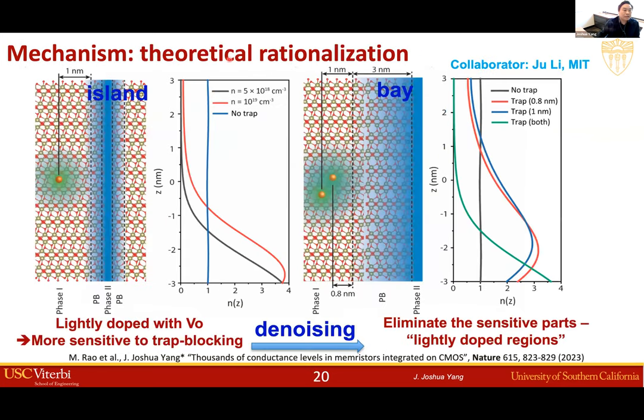So we further use a theoretical simulation to understand why such incomplete channel can give us the RTN noise in the island case and the bay case. Let's just look at the island case. This is an incomplete channel. And it turned out that this incomplete channel can be sensitive to a charge trapped nearby. So without a charge trapped nearby, the conduction of this channel is the blue curve. It shows a reasonable conduction.